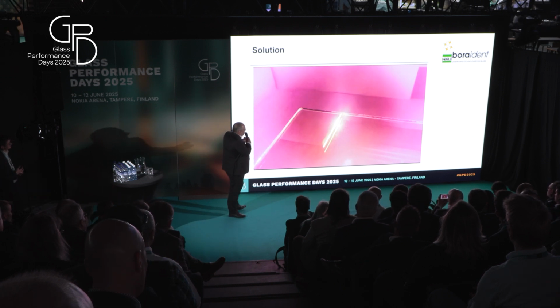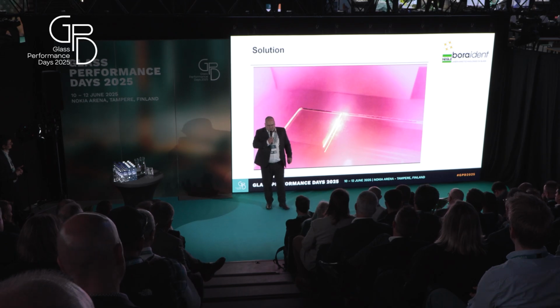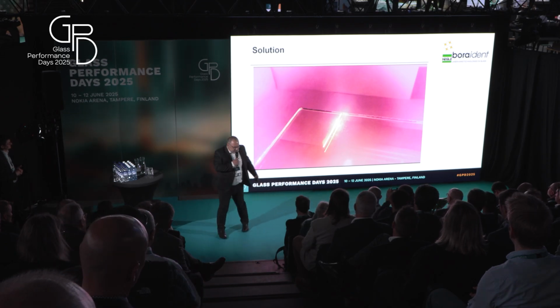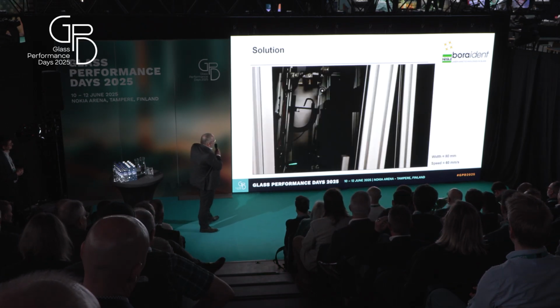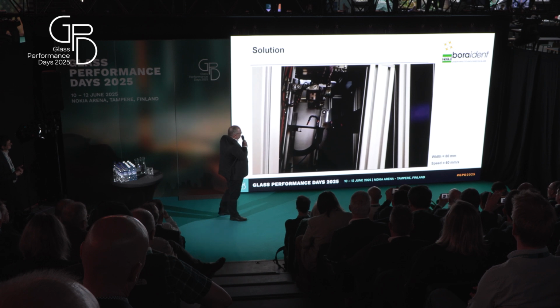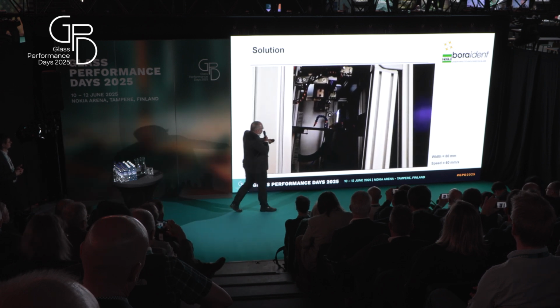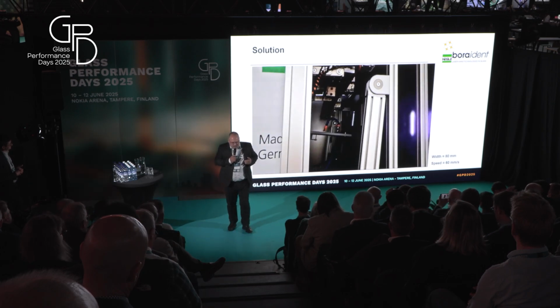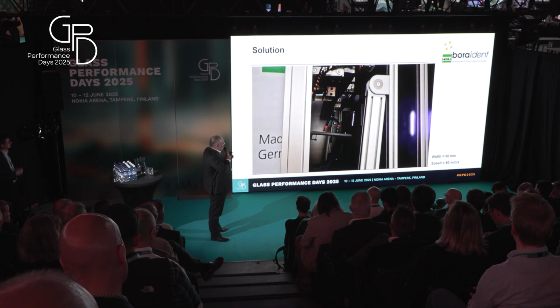And this leads in the end to a line that we can move between the optical tool and the glass itself. And this is the process we have at the end, that the line is running over the workpiece, and this is a big picture from the laboratory state. And last year at glasstec we introduced the first machinery solution, as you can see here, a demonstration tool where we are able to run a stripe of 80 millimeter with 60 millimeter per second speed. You see a lot of material we have here. An important point is to exhaust this material in a careful way to have afterwards a really, really good result of the optical quality of the removed area.